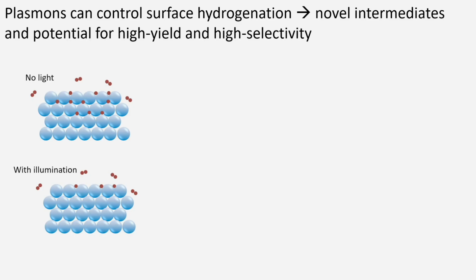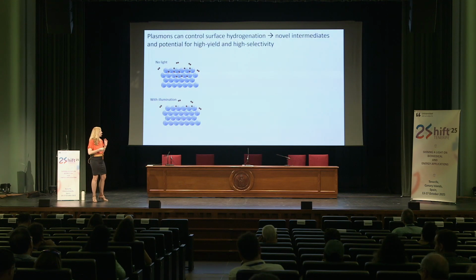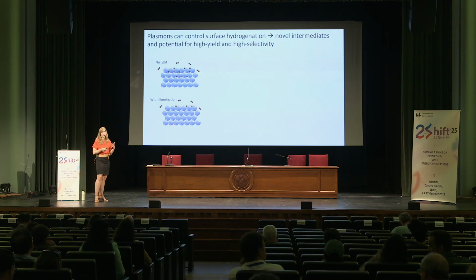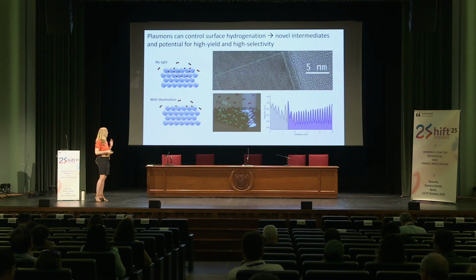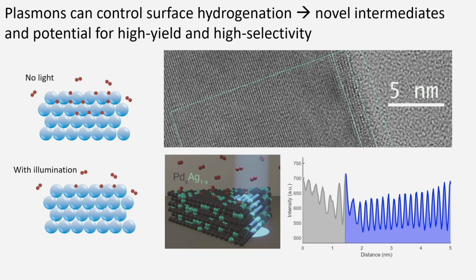So integrated over a large number of experiments, of which this is one example, what we've learned is that you have hydrogen that is entering the surface and subsurface of your catalytically active nanoparticle, and light almost becomes a new reagent with which to control the absorption and desorption of hydrogen at the surface and subsurface. So basically, light gives us the ability to control hydrogen on demand.